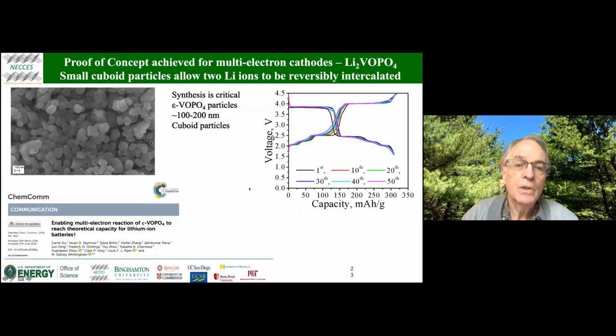This is the structure of the material. Little single crystal cuboids. These are 100 to 200 nanometers in size. Using other synthetic techniques, we can make much larger crystals, but they had a very poor cycling behavior, and if you used high energy ball milling to make them smaller, then you damage the structure, including, in fact, changing the lithium sites that were occupied.